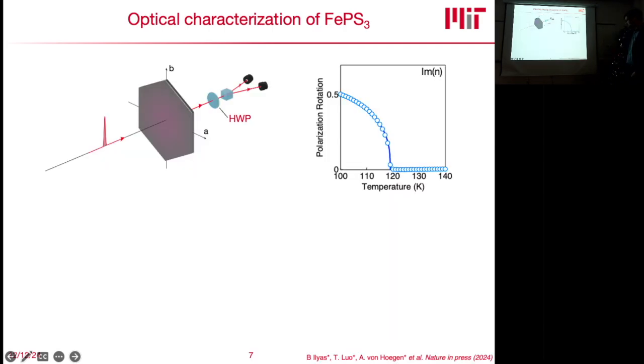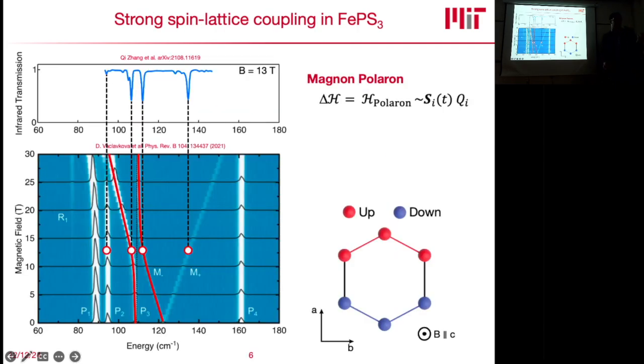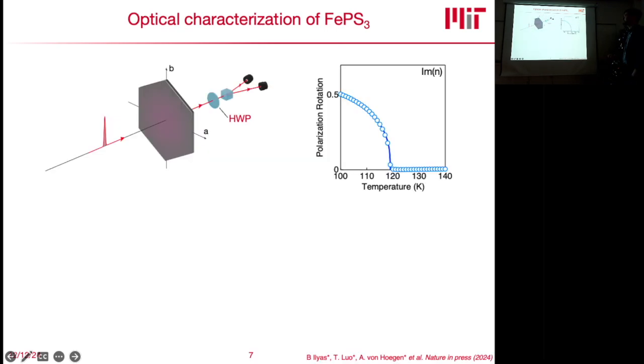And so this is our first step to controlling this material for these experiments, right? We have this type of intrinsic coupling in this material, the strong coupling between spin and lattice, and this is something that we need. The next step is, can we probe these features? Can we probe the magnetic state in iron phosphorus trisulfide? And indeed we can. How we found this out is we send a laser pulse through and analyze its polarization state, in this case with a half-wave plate, which allows us to measure the polarization rotation that our sample induces when our laser beam passes through it.